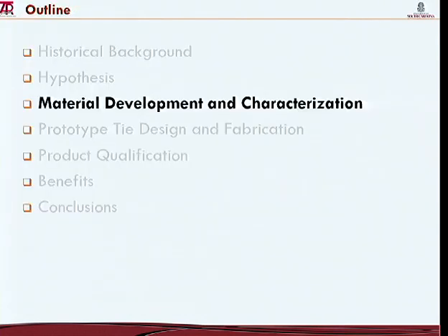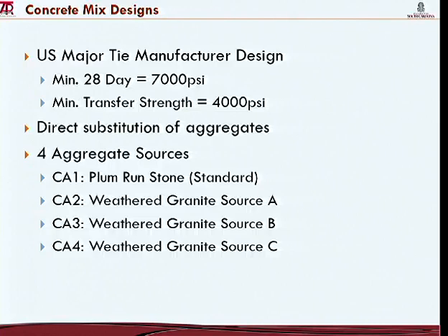So here we departed on developing the material. Same manufacture and design. The only thing we changed was direct substitution of a material. We just wanted to change one parameter to make sure that what we record in our studies makes sense, and we can find out why. So the specs: minimum 28-day strength 7 KSI, and the strength at transfer 4 KSI. We did direct substitution of aggregates and considered 4 aggregate sources. CA1 is what is used by the manufacturer, a limestone, and CA2 through CA4 are the weathered granite from 3 different sources.